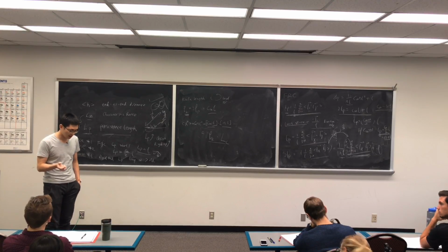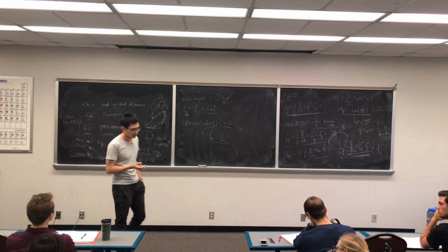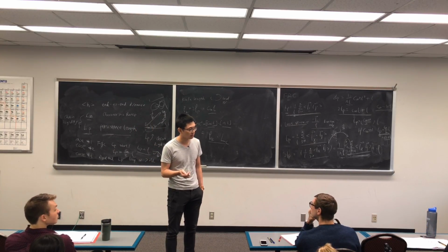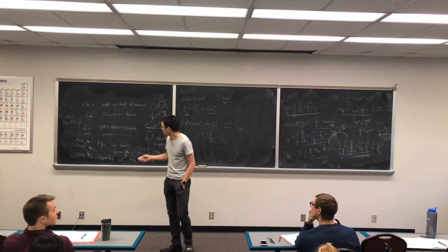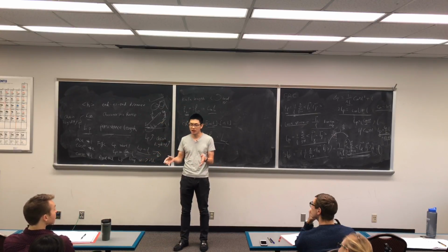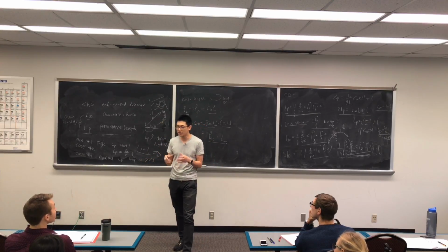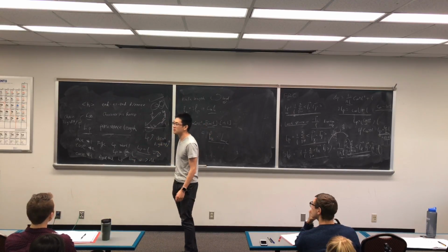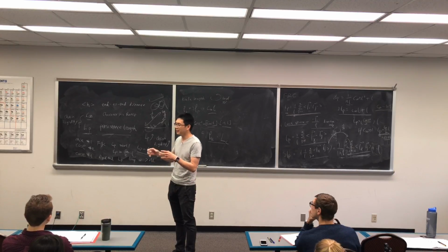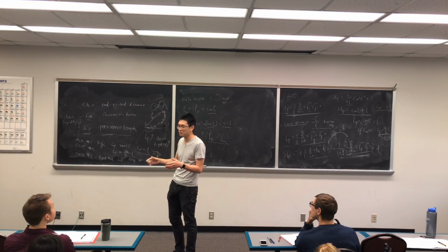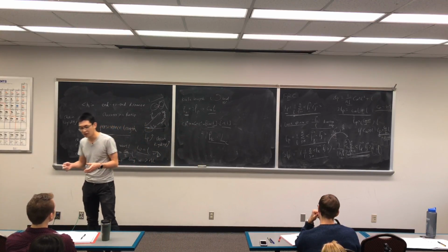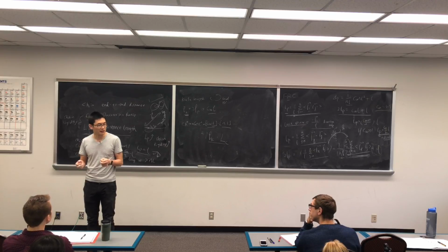And the worm-like chain is probably more critical for real-world application. As we talked about, not every polymer has a backbone made entirely of carbon-carbon bonds. What if you have a benzene ring in between? Then what we described here is not valid because these 3 bonds are tied together. If one bond rotates, the next 3 bonds are going to rotate together with it. How we handle this type of situation is what we're going to talk about in the next class.